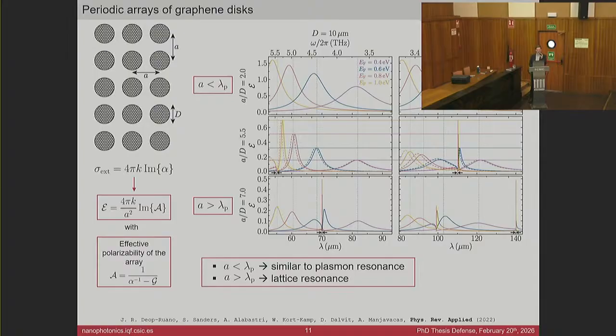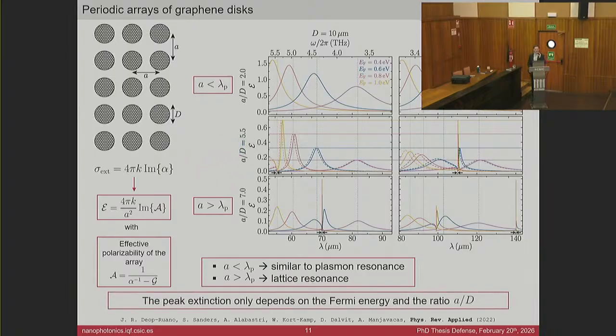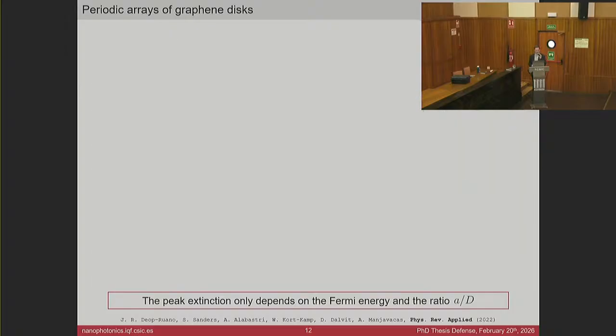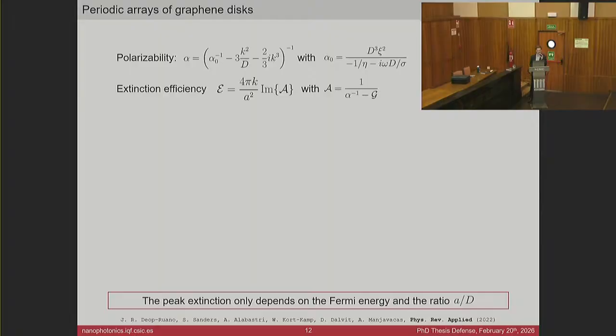So it looks like it doesn't depend on the diameters independently, but only on the ratio of the period to the diameter. To analyze this in more detail, I calculated analytically the peak extinction efficiency. I did so by applying the definition of the extinction efficiency, the definition of the polarizability array, applying all the analytical expressions that we already know, and imposing a resonance condition in which, as we saw before, the inverse of the polarizability is crossing the lattice sum.